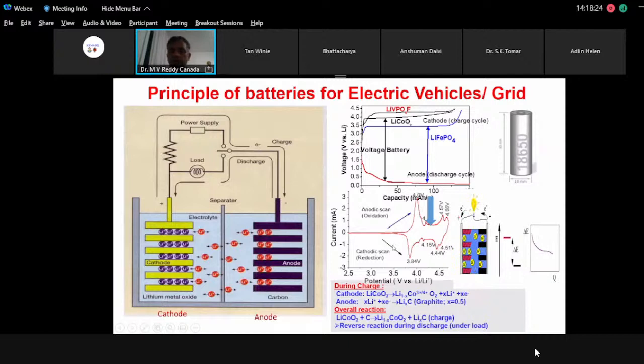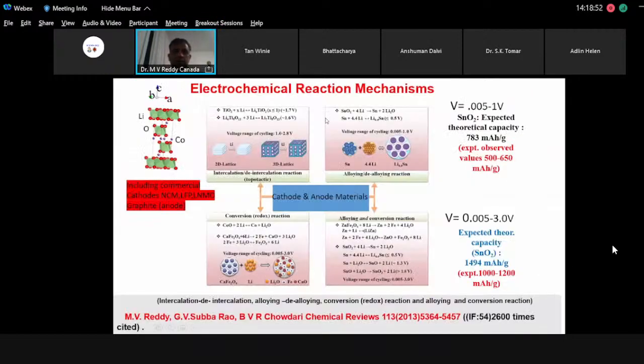The same thing we can plot as voltage versus capacity. We can see almost 3.9 volts. For iron phosphate it is 3.5 volts, and for lithium vanadium fluorophosphate it is about 4.2. Always remember, a good voltage matters, because the energy density is the voltage difference between the cathode minus anode multiplied by the capacity. This is the energy density of any battery. These are very important points to remember.